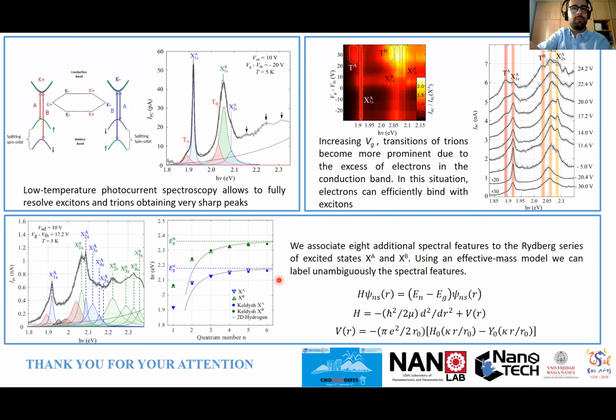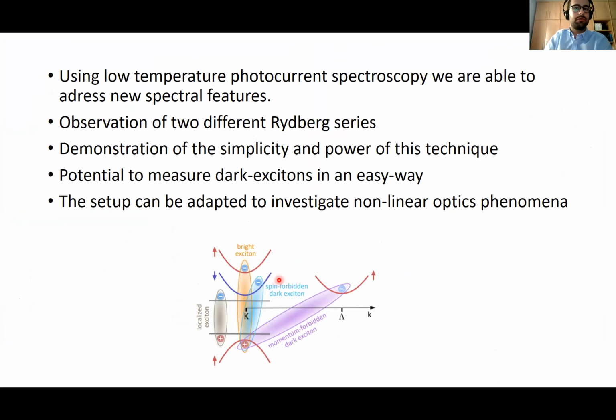Our next work, in my opinion, has to be how to try to measure these dark excitons with this technique, because the only thing that we think we have to do is tilt the sample a little bit with respect to the excitation light, and this change of the direction of the electric field can allow us to see these different dark exciton states.